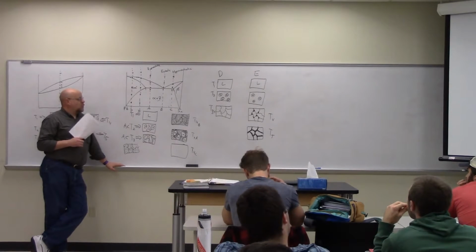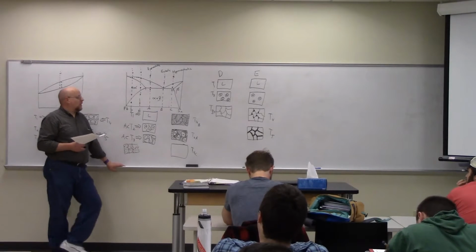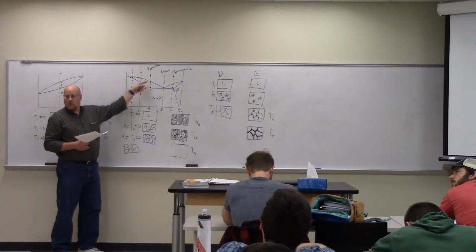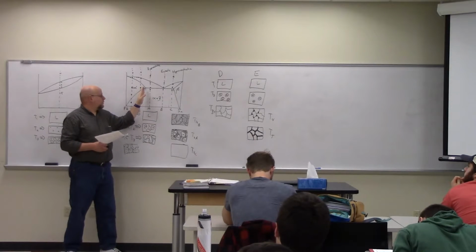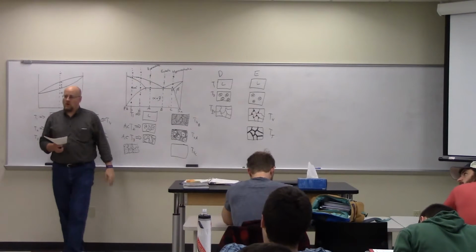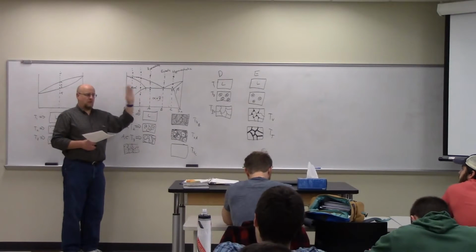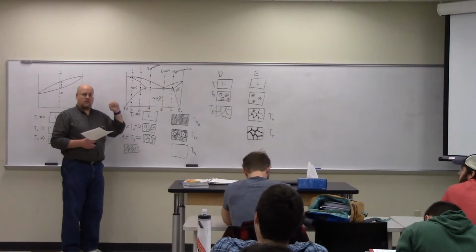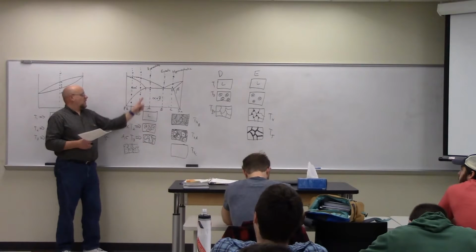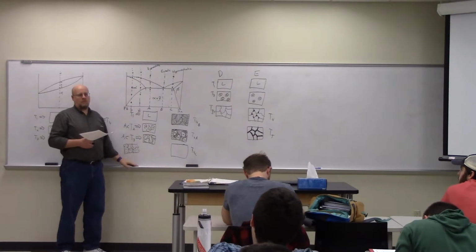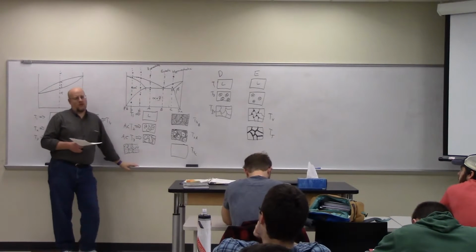So you notice there is no eutectic in any of D and E, because no material was ever a eutectic liquid that crossed this boundary. And I could do the same thing out here in the beta region. So only between here and here do I get any eutectic material. And the closer I am to the ends, the less of this there is in the spaces between the grains. Yes? What happens if you're at the ends of the eutectic area? Right here? So in theory, then you never form eutectic. You have to actually be inside of that grain. It's not likely you're going to hit a point.